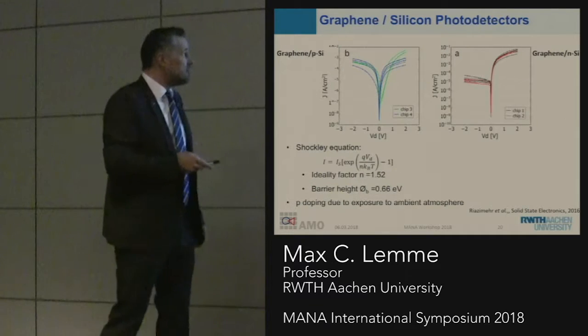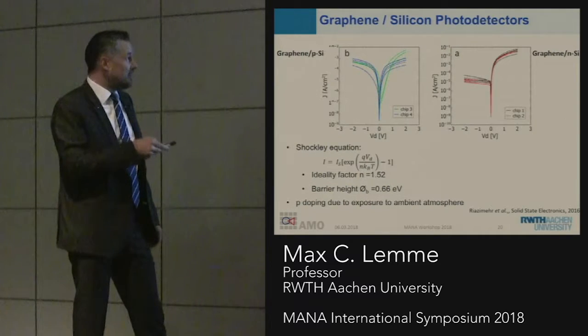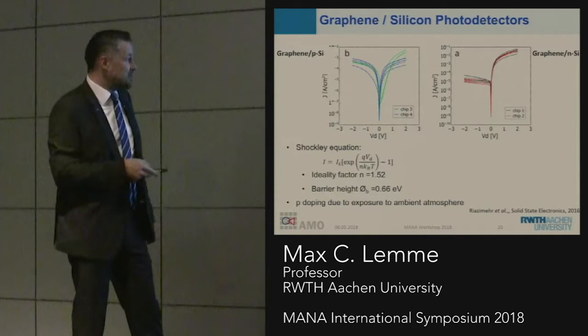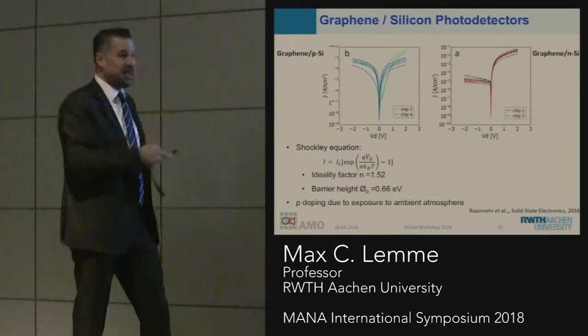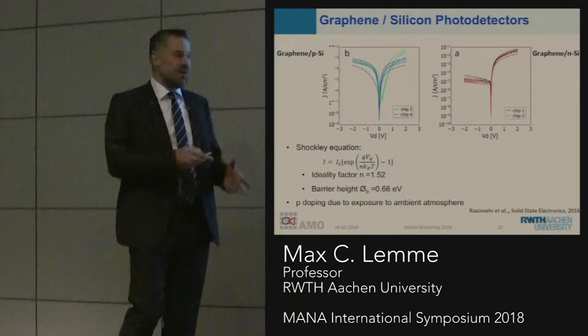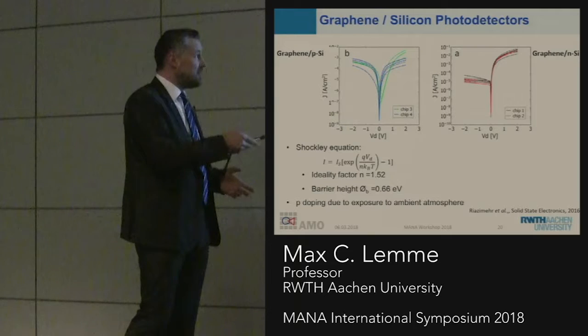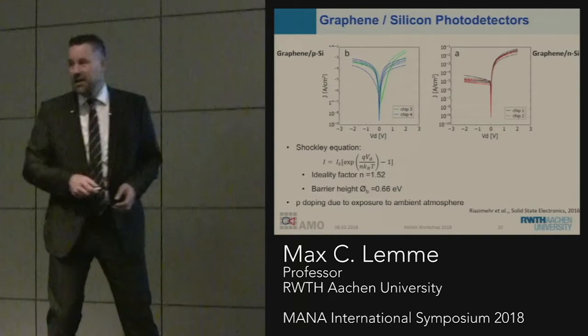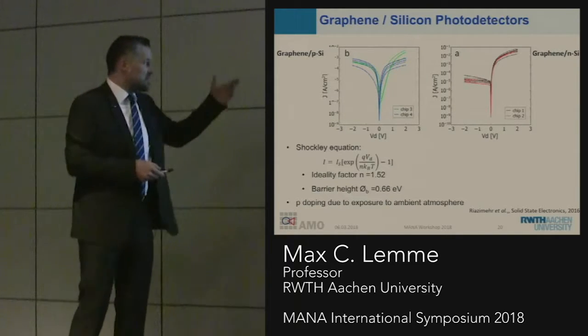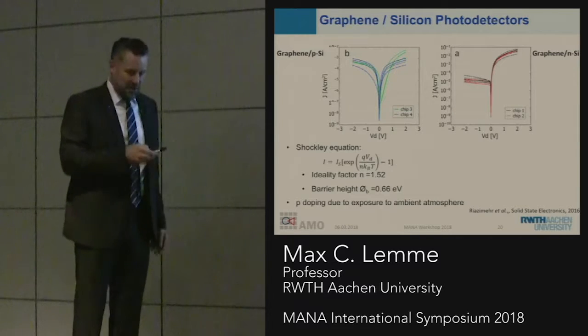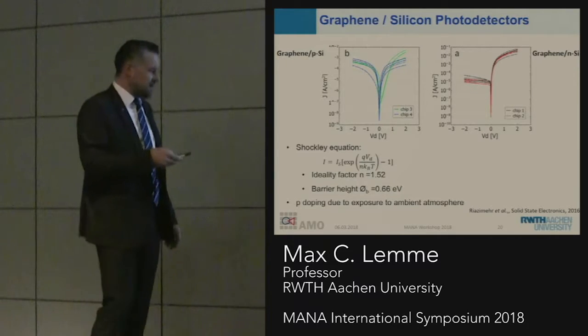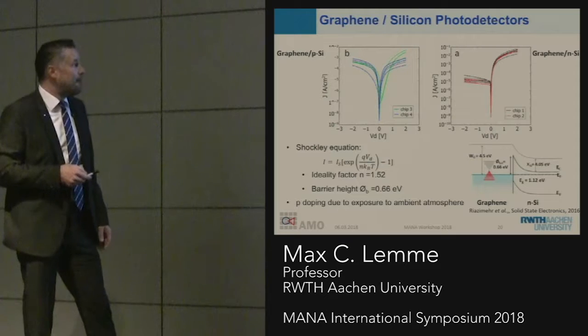You can see if we use P-type silicon, it doesn't show very much rectification, but if we use N-type silicon, it's very clearly a diode. That has to do with the fact that graphene gets P-doped when it's in air. So this is just an ohmic contact, whereas here it's a Schottky barrier. Then we can extract the ideality factor and the barrier height, and so on.